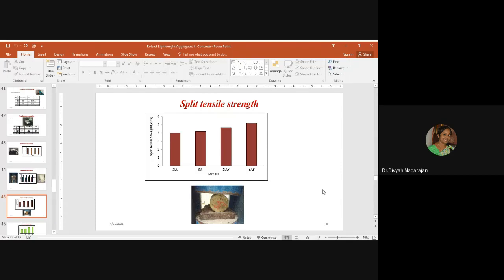But it is not due to the bridging effect of the fiber, because basalt fibers are short and discrete fibers. There will not be much bridging effect when using basalt fiber. Steel fibers serve this purpose a lot, but basalt fiber is added to this concrete in order to avoid the cracking of the aggregates when subjected to loading, since this concrete has to be used in structural members.